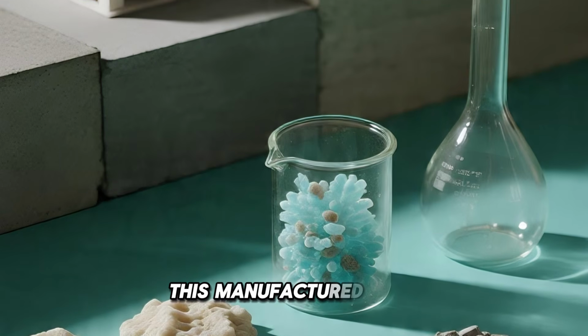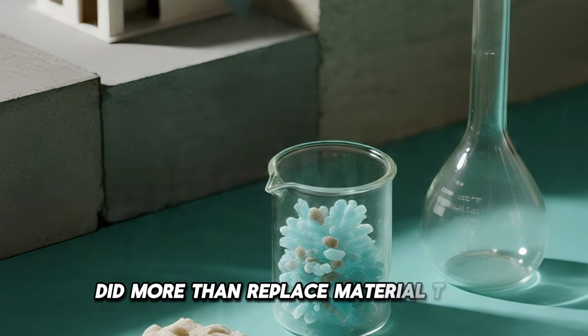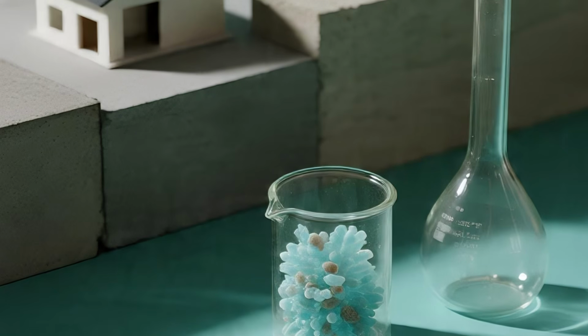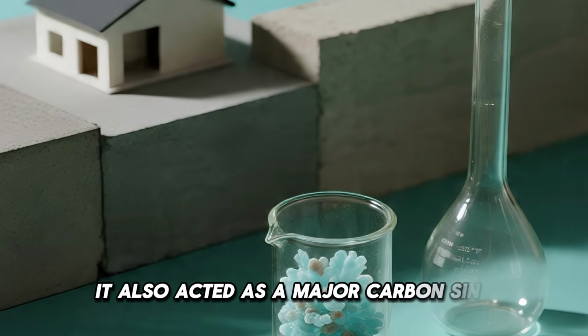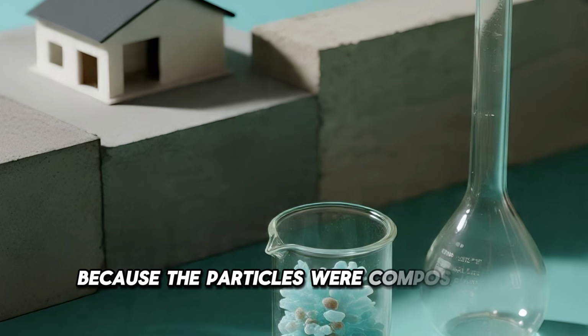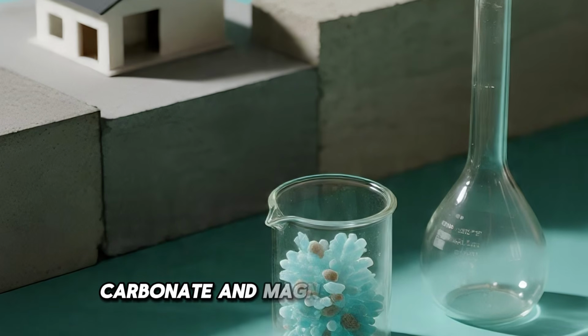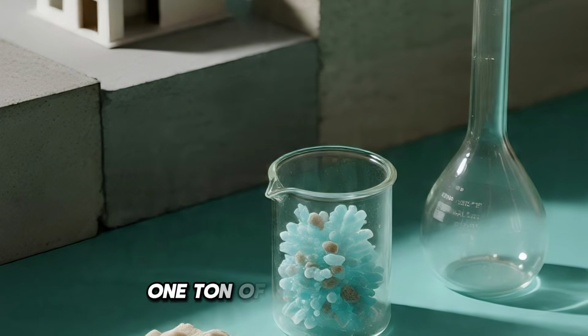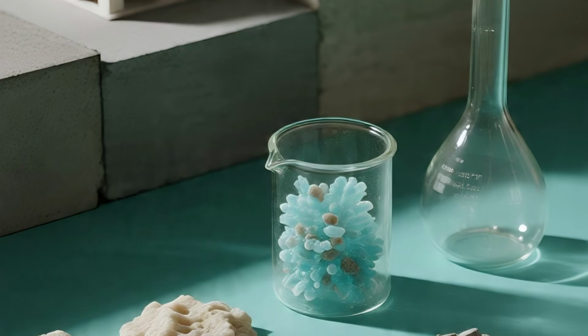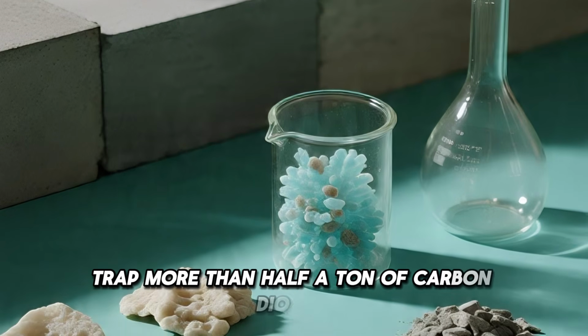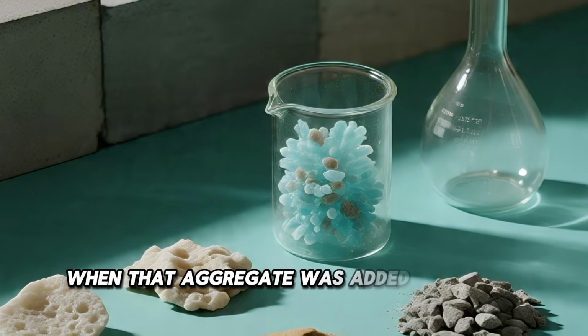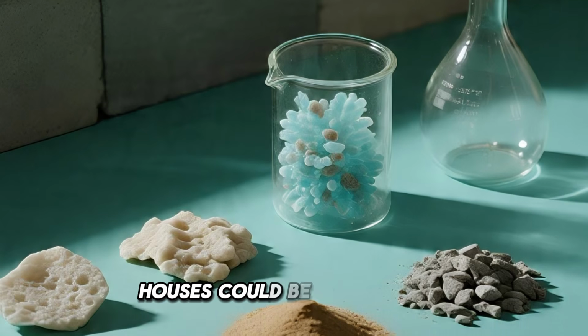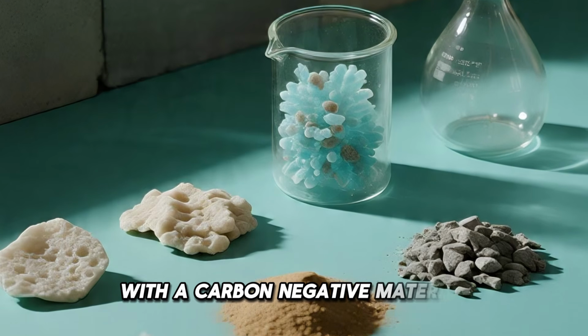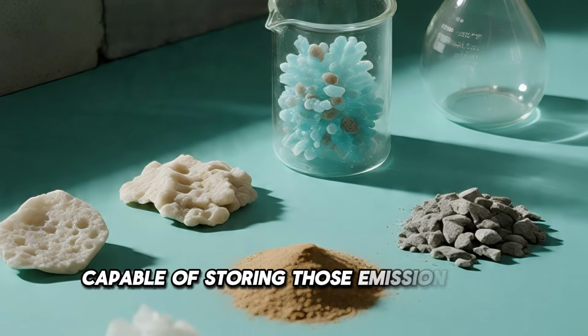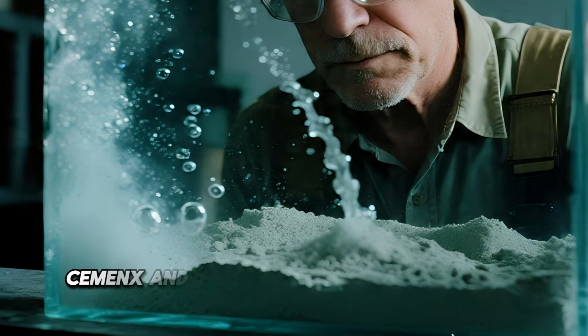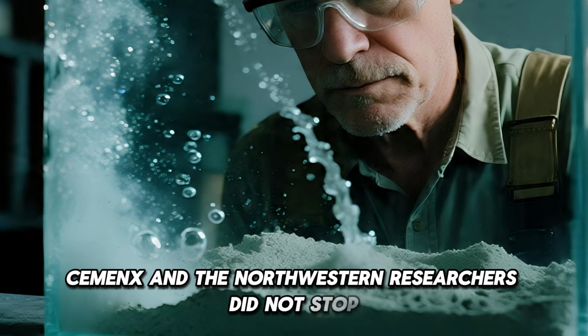This manufactured sand did more than replace material taken from rivers and beaches. It also acted as a major carbon sink. Because the particles were composed of calcium carbonate and magnesium hydroxide, 1 ton of the grown sand could permanently trap more than half a ton of carbon dioxide. When that aggregate was added back into concrete, houses could be constructed with a carbon-negative material capable of storing those emissions for centuries. Cemex and the Northwestern researchers did not stop there.